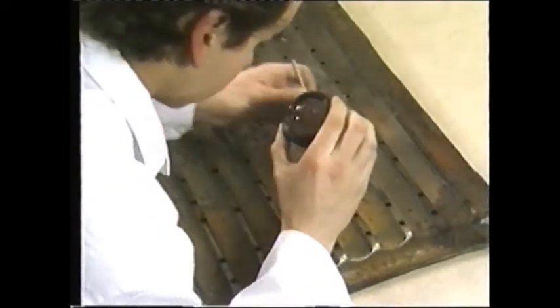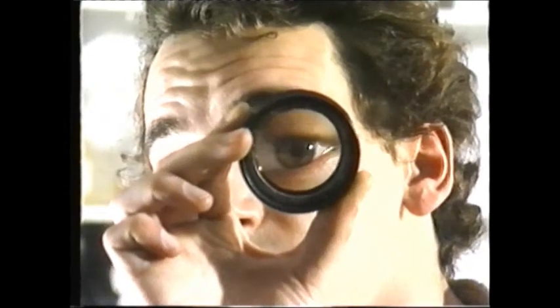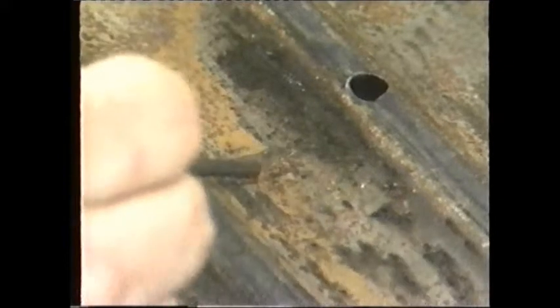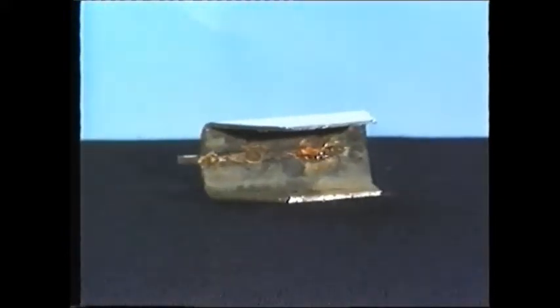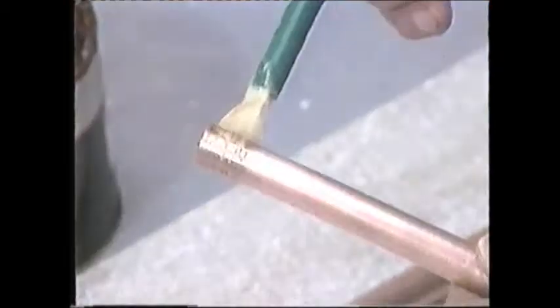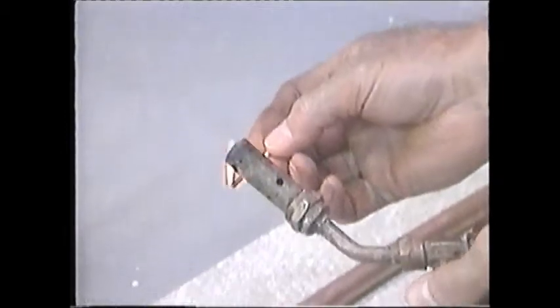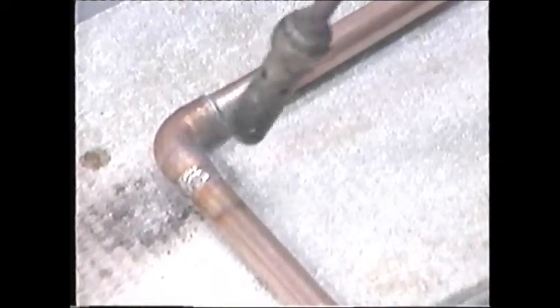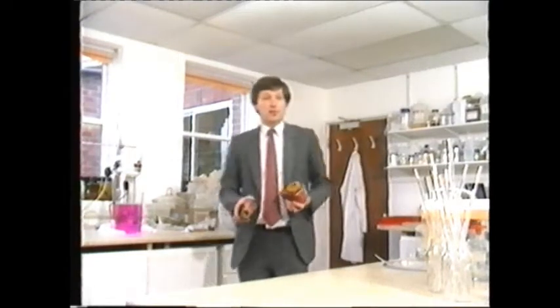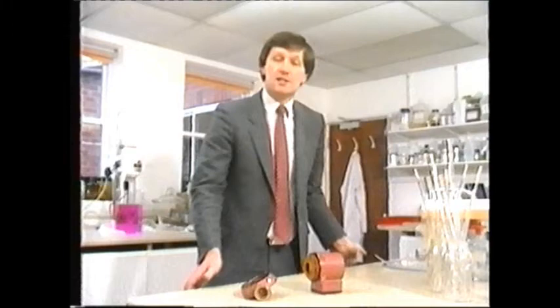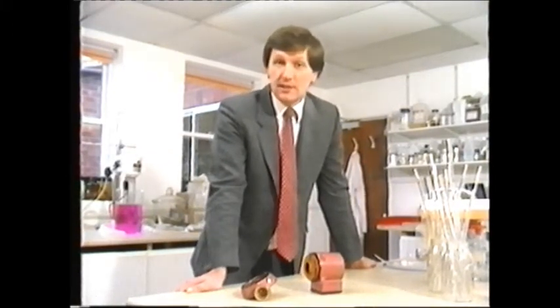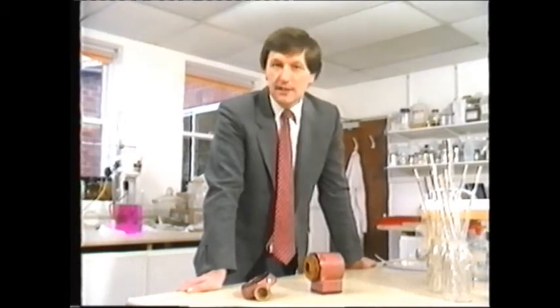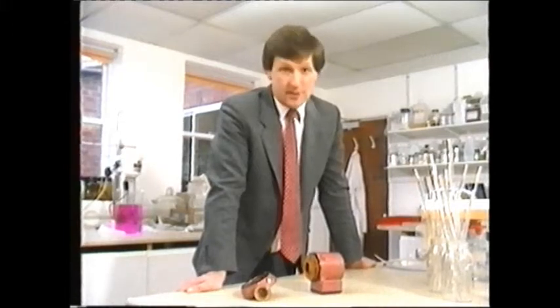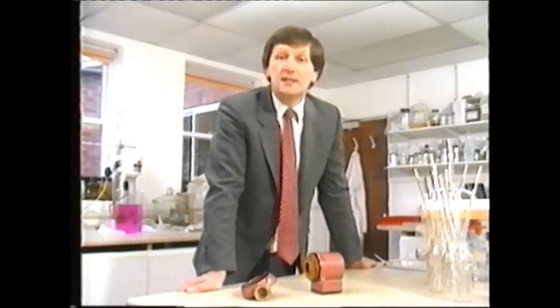Electrolytic corrosion can also be accelerated by the presence of crevices, which form, for example, under deposits of corrosion debris or even brick dust and sand, which we know can all too easily be left in a new system. This is often called crevice corrosion. Self-cleaning soldering fluxes are also often associated with corrosion damage. It's a matter of some controversy, but there's no doubt that excessive amounts of flux residues can cause short-circuited electrolytic cells by depositing copper oxide directly onto steel. Damage can also be caused to pumps and other control equipment. However, sensible use of fluxes and correct flushing procedure at the commissioning stage will do much to eliminate these problems. The conclusion is simple. In heating systems where mixed metals are used, and that's just about all of them these days, corrosion is inevitable and continuous.